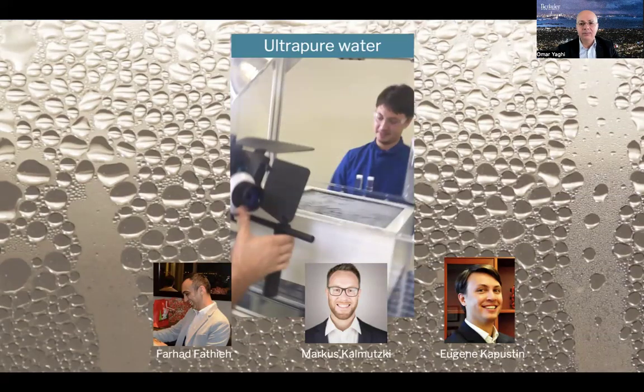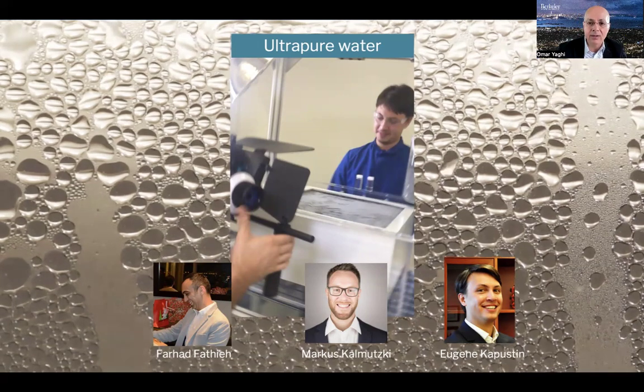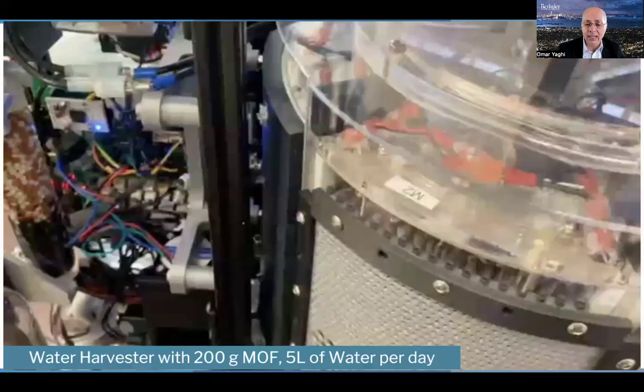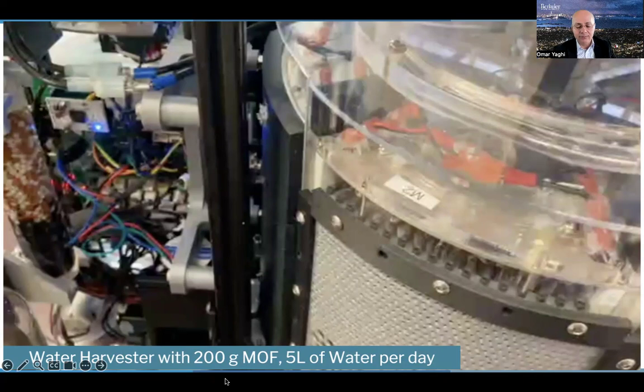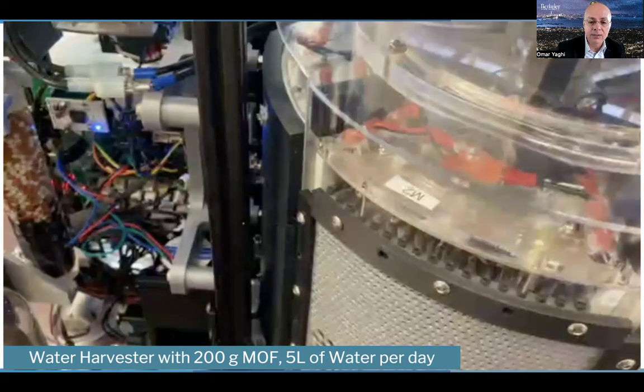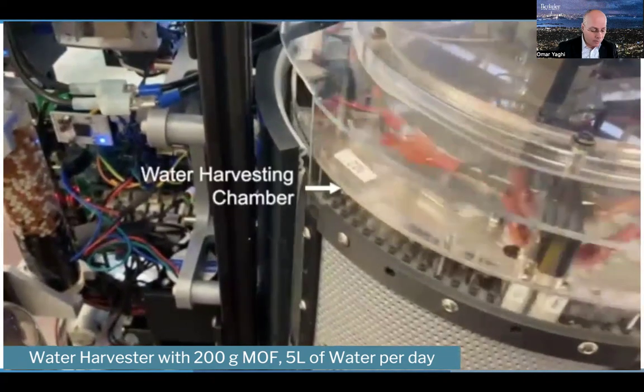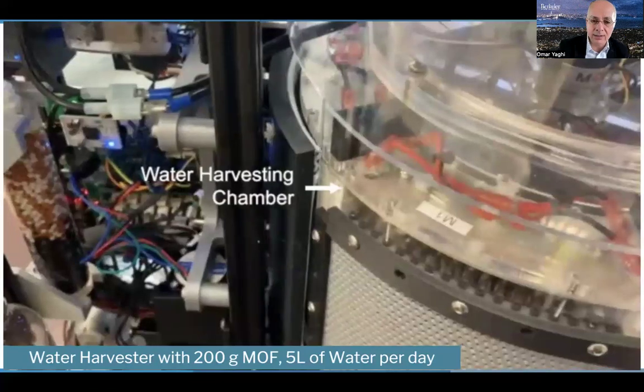This is supposed to be a movie to show that, in fact, the water is clean and has no organics. There's no metal, no organics in the contamination. It's ultra pure. We also have a device that uses 200 grams of MOF and delivers 5 liters of water every day. This is an electrified device, unlike the one deployed in the desert that operates only under ambient sunlight, with no electricity. But this works in the same way I just described.